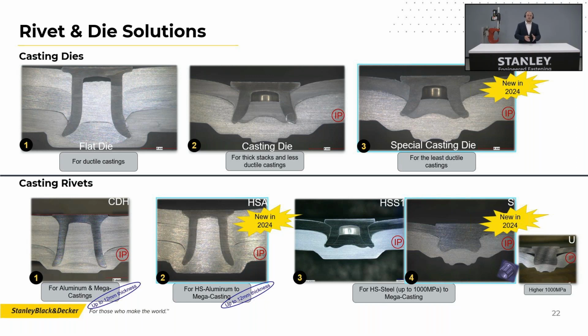First one is just the flat die. I'm talking about the die, not about the rivet in the first picture on the top left. So it's a flat die that you can use for more ductile castings, meaning if they have a T7, right, or a T6 heat treatment, then you can use them. These flat dies are perfectly working. Then the second picture, it's a casting die that we developed, and you can get that with flow barrier feature or without flow barrier feature. In this picture, there is the flow barrier feature existing, and you can use this die for lesser ductile castings.